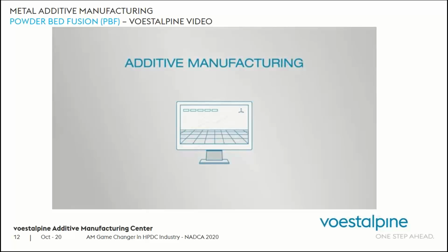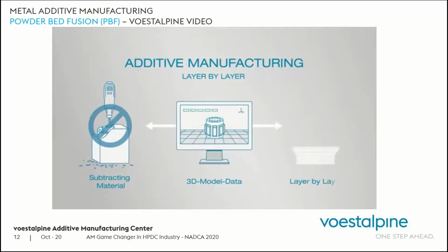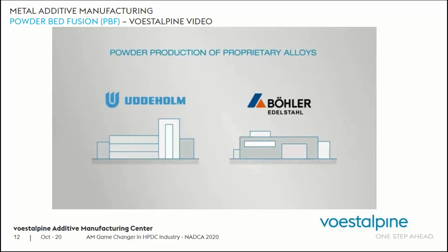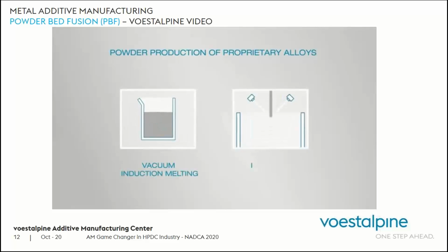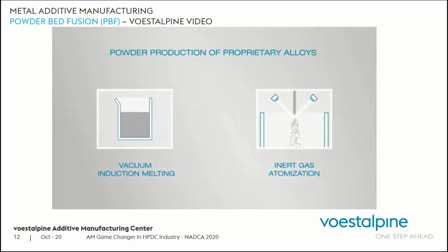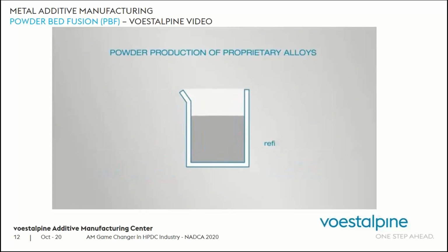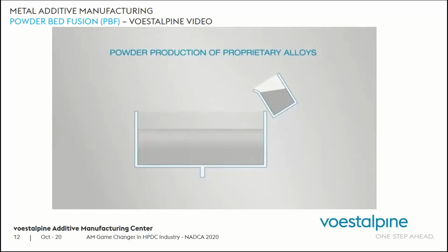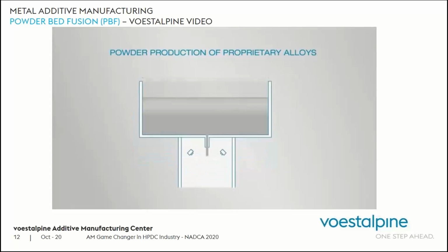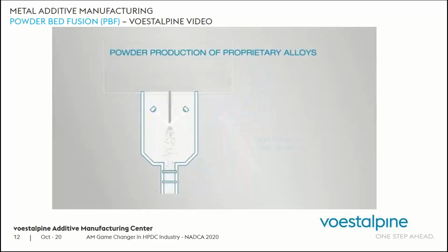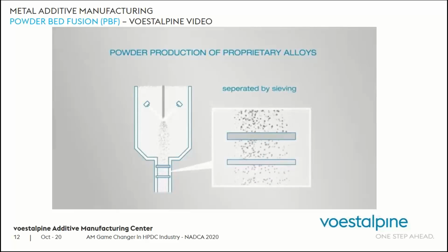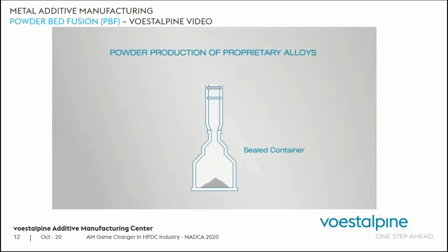Objects created using additive manufacturing are built up in layers according to 3D model data. Instead of cutting material away, it is added layer by layer to form almost any shape you need. For this metal processing, we produce high-quality metal powder within our group at Böhler and Uddeholm. This is typically done by vacuum induction melting and inert gas atomization. The powder can be made from metals such as steel, nickel-based alloy, and cobalt chrome. First of all, the melted metal alloys are refined and degassed. This refined melt is then poured into a gas nozzle, where it is disintegrated into metal powder by a high-pressure gas stream. The different powder fractions are then put through a sieve to separate them before they are sealed in containers. Then we can start creating.